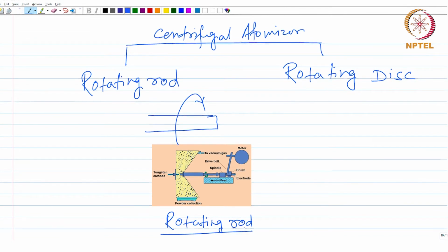And the main parts of this are a feeding mechanism here, which can feed this rod, which has to be melted. And of course, you have this drive belt and the spindle for feeding and rotating this rod, which melts at this chamber. In this case, as you could see, it is done with the help of a tungsten electrode. That means we take the help of an electrical arc to melt this rod, which is being fed into this end where the tungsten electrode is, and it is melted with the help of an electric arc.